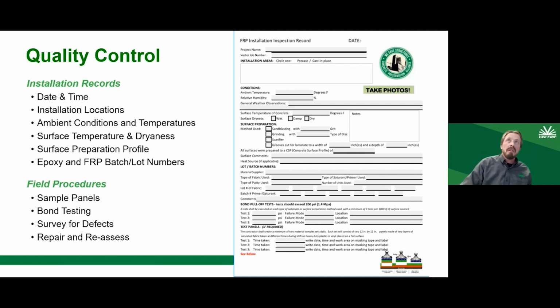And then we want to document the lot and the batch numbers to make sure that if down the road we've had a bad batch or something was wrong along the way, it's documented. We know that, hey, beams 2 through 5 have this lot number, and then the other beams are that lot number. And then of course our bond pull-off tests. That's one of the more common ways of ensuring that we've got good bond between the FRP and the parent concrete. And then of course a visual survey to see if there's any bubbles or delaminations along the way.